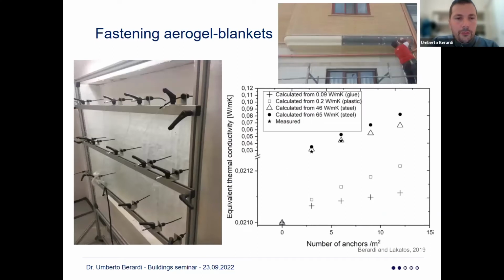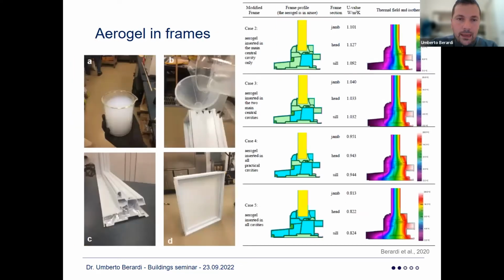We also have been working on a few other aspects of aerogel products, such as how we attach an insulating product. If you have a super insulating product and you attach it with materials that are not insulating, as we often see happening, we get a lot of thermal bridges. So we have also been developing special glues with low thermal conductivity to attach these materials and avoid thermal bridge issues. We've also been working with Alessandro, the chair of today's talk, to try to reduce the thermal transmittance of windows, both in the frame part as well as in the window part. The work is both experimental as well as numerical. The idea is to understand which cavity really makes more sense to insulate with aerogel granulars, and what the beneficial impact is of a frame with aerogel in the cavity.